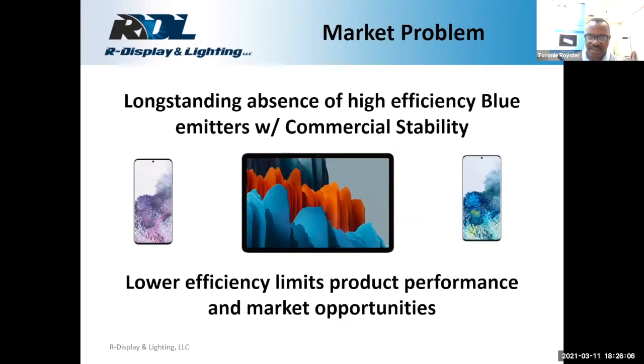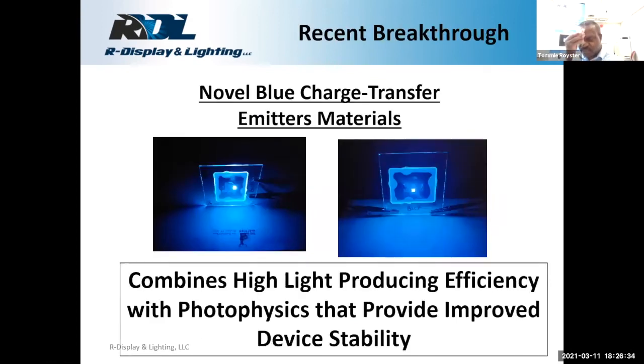And just to reiterate what I earlier stated, there's a long-standing problem with establishing high efficiency blue emitters with good commercial stability. Typically, there's a trade-off between good stability and efficiency. And it has been very difficult to combine the two. However, we're extremely excited about a recent breakthrough with our new charge transfer emitter materials, in which we have been able to show the combination of high light producing efficiency with photophysics that provide good device stability.